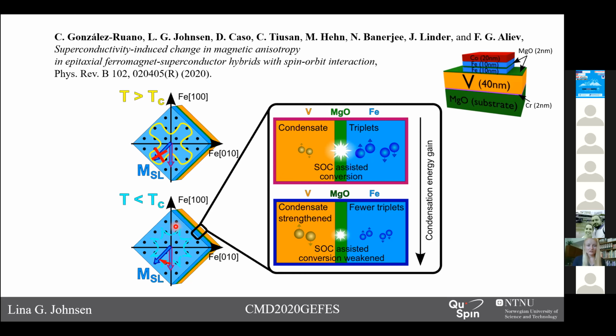While below the critical temperature, a new minimum occurs so that we can rotate the magnetization by pi/4, as we've shown in our theoretical predictions. This is caused by a strengthening of the condensate due to a weakening of the spin-orbit coupling assisted conversion for this direction.